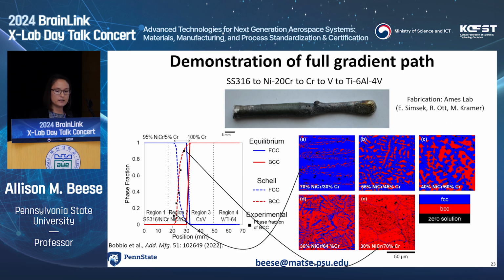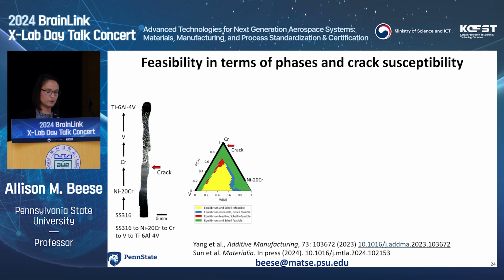This was fabricated by Ames Lab. It wasn't optimized in terms of processing parameters, but what we were interested in was, do the phases actually transition as anticipated? Meaning, do we go from FCC as equilibrium and Scheil predict to BCC as these both predict? And we saw that we very well followed the Scheil predictions. However, this was good in terms of avoiding intermetallic phases, but we did still have cracking when the chrome was introduced, so up in this corner here.